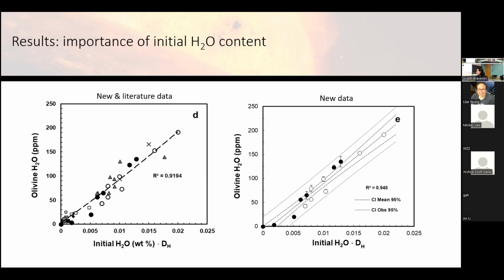And once we account for the initial water content put into the sample, we see that these samples do indeed fall perfectly within an explanatory trend line. This is also important because we don't necessarily know that magma oceans contained multiple weight% of water. It could be that they were only nominally anhydrous, in which case we desperately do need to consider the initial water content of these experiments.